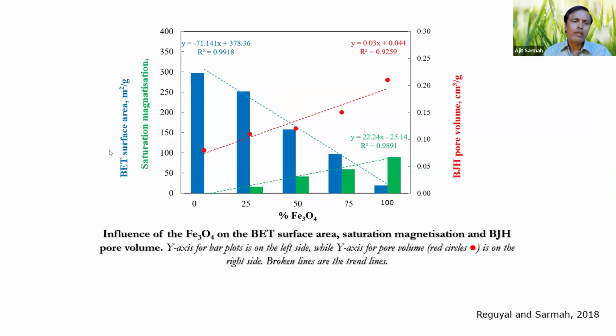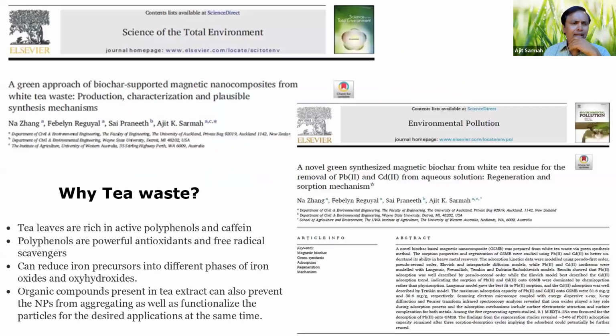Now, this is another one, looking at how surface area can be plotted as a function of different percentages of Fe3O4, because the influence of Fe3O4 on the surface area can be evaluated by simply looking at this. You see these blue bars are the BET surface area. The Brunauer-Emmett-Teller surface area of the biochar is basically decreasing. However, the saturation magnetization is increasing. So it's a trade-off. Here we studied the influence of iron oxide on the surface area and saturation magnetism, and also on the pore volume. This is on the pore volume side. It's a bit technical, so I'm not going to explain that.